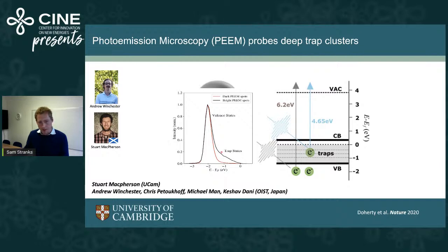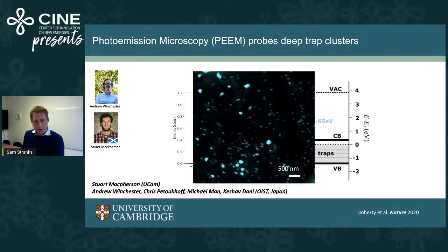Obviously, some regions have lots of trap states in this region. Other regions are quite clean in the subgap region. And so this allows us to look at spatial maps around this energy here, so we can start to look at where these traps are, for example. And this is an example of a trap distribution map. This is looking at this subgap energy and then plotting it spatially.